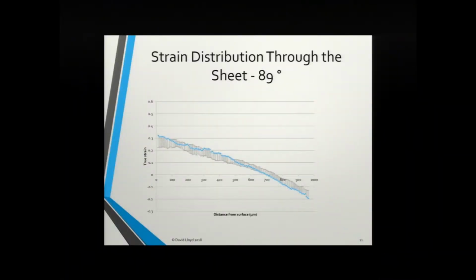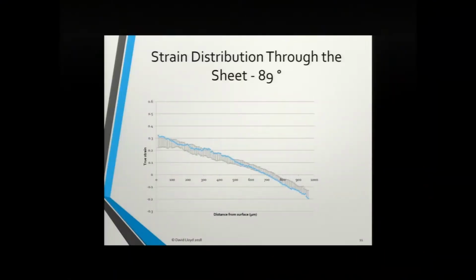This shows the strain distribution through the thickness of the sheet. So we've got a bend sample, and we're looking at this plane. This shows the distribution of strain with distance from the surface for a bend angle of 89 degrees. You can see that as we move from the surface, which is here, into the sample, the strain drops, as you'd expect from the equations, and at this point, which in this case is somewhere around 700 microns from the surface, the strain goes to 0, and then into compression if you carry on. That distance there gives you the position of the neutral axis from the surface.